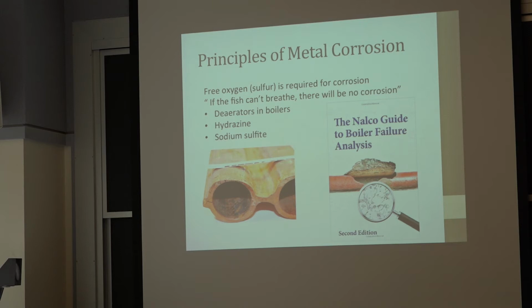And these were the walls of the heat exchanger, one of the heat exchangers for the boiler. And they had water going through here that they were heating up and using in other parts of the process for steam and stuff. After about 1 or 2 years in production, they went from a thickness like this in the steam tubes to a thickness like this, and then they decided, that's probably corroding too fast for us. And this is because they had these sulfur compounds and other stuff. It was hot steam. And so they decided to go in and plate the whole thing with Inconel, okay?